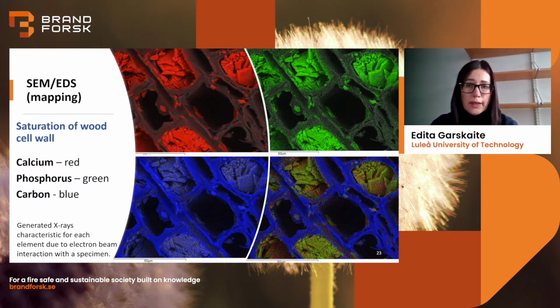And then you can assign those elements different colors, and this is just to help us visualize. And then you can see a distribution when you perform a mapping of this certain place which you investigate in the scanning electron microscope. So when you get the images processed, what we can see here is that we have not only inside these crystals formed, but we also get saturation of the cell wall.